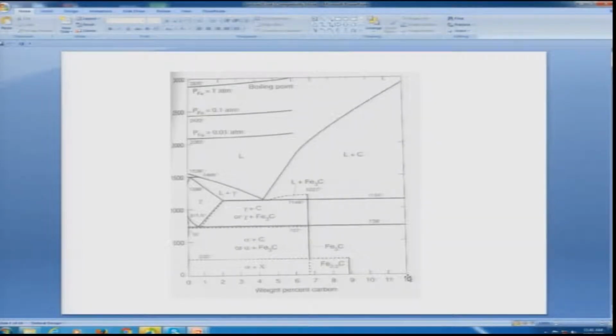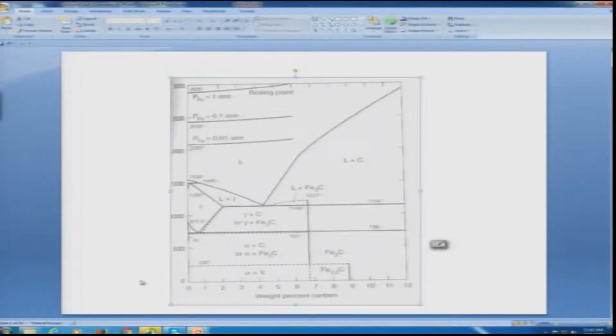As we are going to discuss pearlitic transformations, especially the eutectoid transformation in steel, we are not going to discuss the whole phase diagram. We will concentrate only on the salient portions required for our discussion. What you see here is equilibrium between two phases: alpha iron, which is a solid solution of carbon in BCC iron, and another phase, Fe3C, popularly known as cementite, which is basically a carbide. And you see the gamma, which is a solid solution of carbon in FCC iron, undergoes a transformation at this temperature.